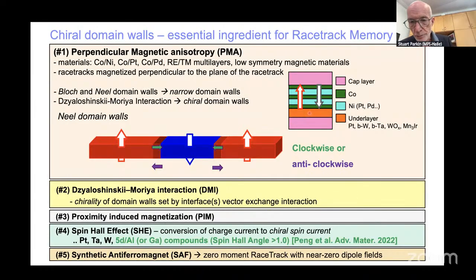This interface breaks symmetry and leads to a very interesting so-called Dzyaloshinskii-Moriya interaction, which means that the cobalt atoms are exchange coupled via the platinum in the neighboring layer. Because the platinum is on one side, this breaks inversion symmetry and leads to a very interesting chiral interaction, which was first proposed many years ago for spin glass systems.